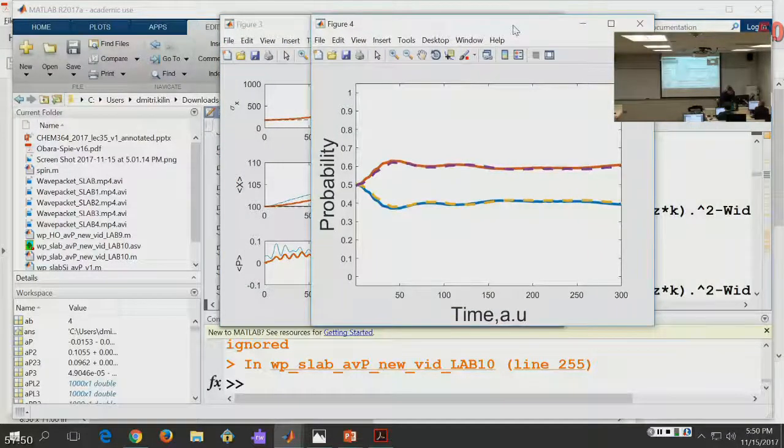Okay, so here at the initial time, the charge is equally distributed over both sides, and at a relatively quick time, 50 atomic units, which is on the order of a couple of femtoseconds, it becomes imbalanced to one side of the cell. Then it stays in more or less a steady state. How quickly it goes does depend on the contact. Right now it is very efficient through bond transfer, because atoms on the left and right side are chemically bonded.